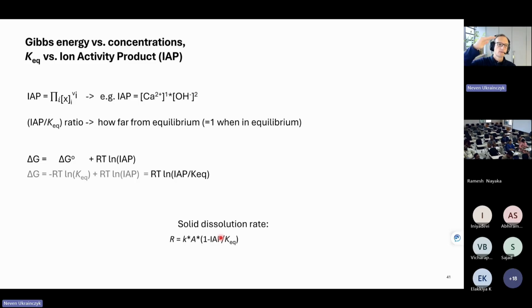The concentration in the ion solution drops, and then you have further dissolution of cement clinker, and everything starts to go in this cycle. It's called the Le Chatelier process. Everything that dissolves again precipitates, and you are basically near equilibrium.